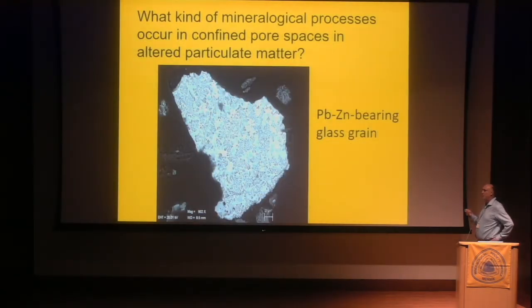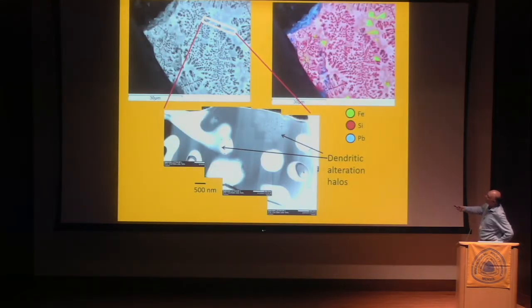Okay, so I showed now how nanoscale processes, mineralogical processes occur in confined pore spaces and altered surfaces, but you can also look at particulate matter and how particulate matter is altered. And for this reason, we went to the same soils, the soils in Timmins, and we took a look at a lead-zinc bearing glass grain, and you can already see here the alteration features, which are dendritic dissolution features. We took a FIB section along those dendritic dissolution features with those alteration halos shown here.